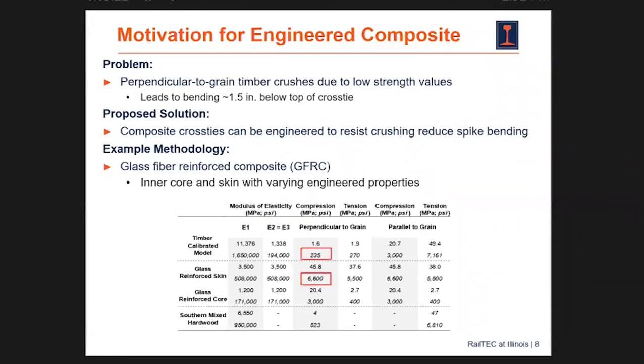And whenever we look at the differences in compressive strength of this perpendicular to grain timber versus the compressive strength of the glass reinforced composite tie, there is a big difference in strength. And this big difference in strength should give us a benefit because we'll no longer be crushing the material. That's our goal. And so if we don't crush that material, the spike can't bend as much. And without that additional bending, then we won't fatigue fail it. That's the goal.